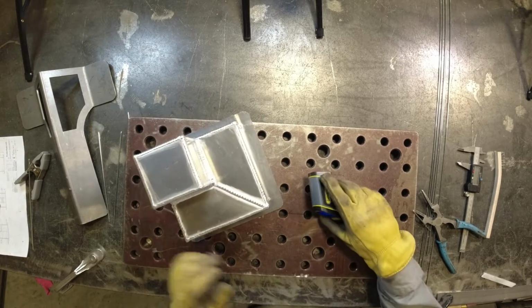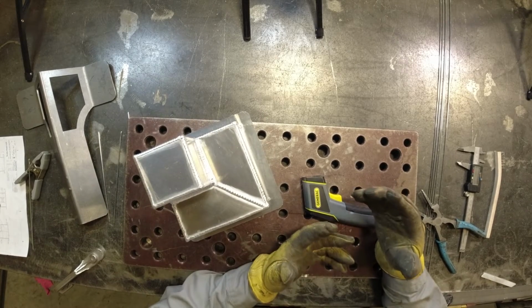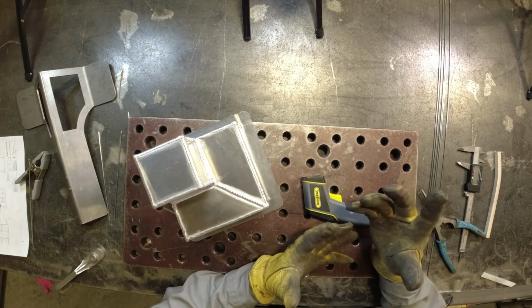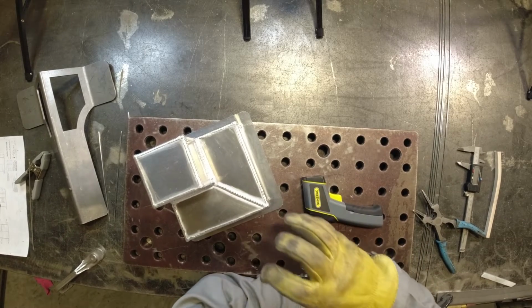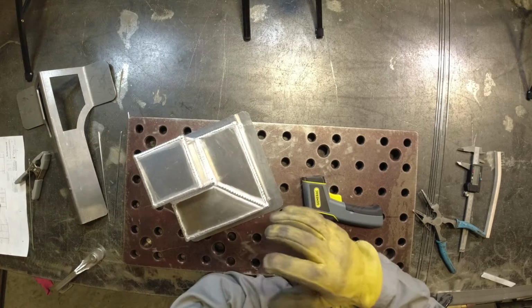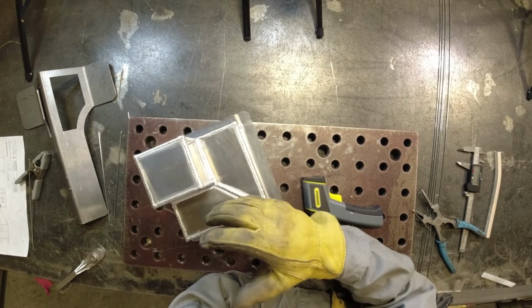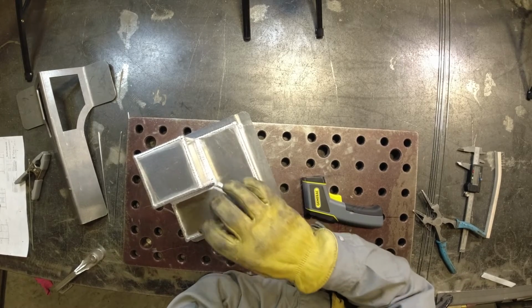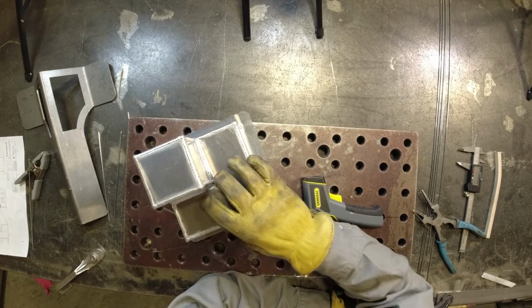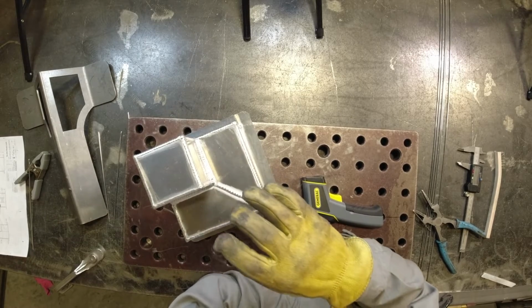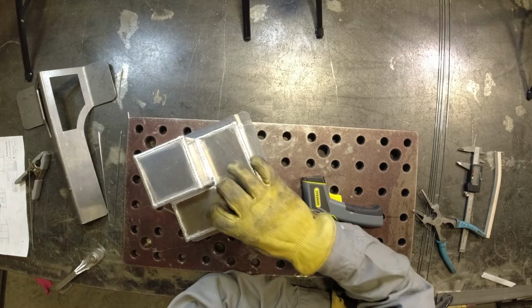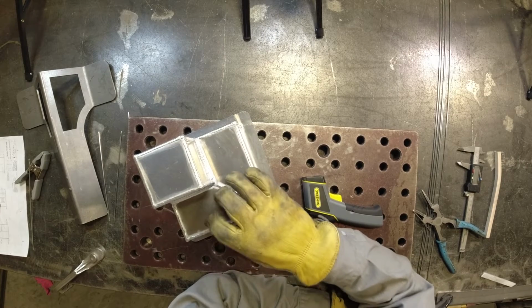So if you are welding this project at 250 amps or 200 amps or whatever you're welding it at, and you are used to starting welding at base material at 70 degrees, 200 amps with 70 degree base material is going to weld a lot colder than 200 amps at material that is at 150 to 200 degrees.